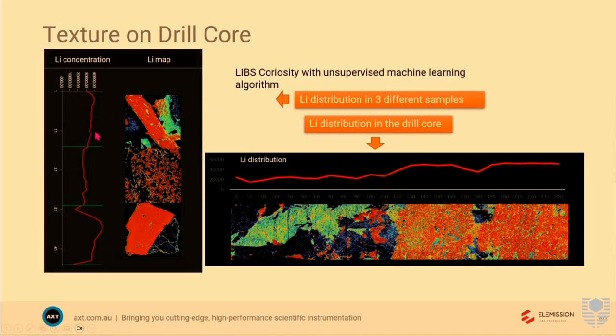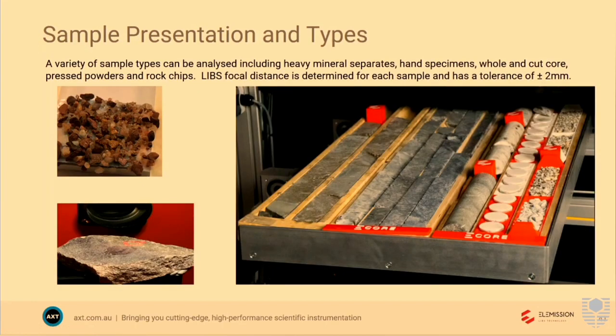This is the lithium concentration, so it's summing it over the edge of the sample. Again, you can see large crystals of, in this case it's spodumene, versus fine crystals. And so when you are zapping an entire length of core, you can actually work out what your quantitative mineralogy is. So you can analyse whole core if the surface height is within 6 millimetres, half core up to 40 millimetres wide, pressed powders if you want an absolute quantitative analysis, or rock chips.